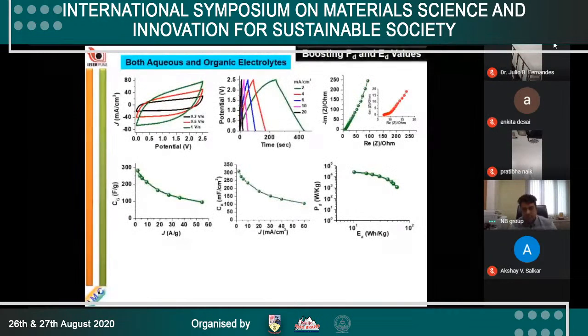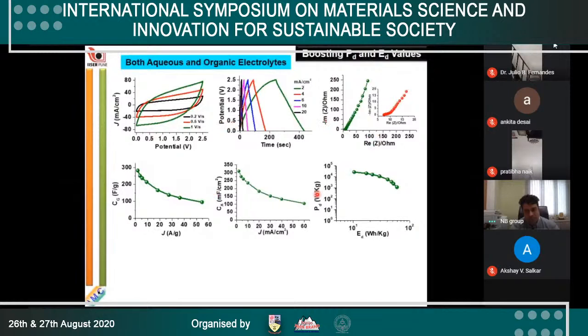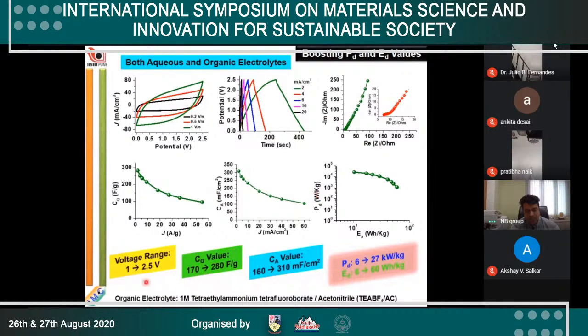Our RGO material is good for both aqueous and non-aqueous electrolytes. To further boost the energy density value, we have explored organic electrolyte. And here are the electrochemical performances. In short, we could increase the voltage range from 1 to 2.5 in acetonitrile. Capacitance values are significantly increased. What is noticeable is the energy density, which is now 88 watt-hour per kilogram, close to lithium-ion battery.